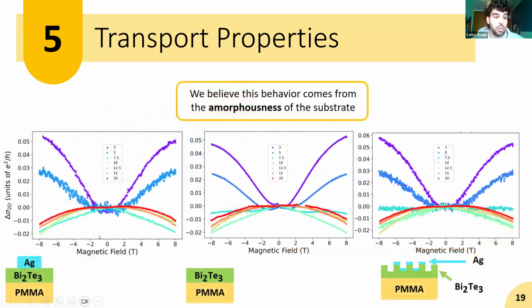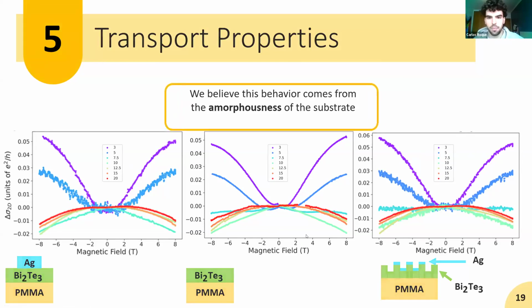We measured this sample again with the silver layer, then a sample with only bismuth tellurium, and then a sample with bismuth tellurium and silver but tailored with grating structures. And we verified that all data exhibit this competition between these two behaviors. So this competition does not come from the silver layer on top. We think that it comes from the amorphousness of the substrate, which is so amorphous that it localizes the electrons, and then the weak localization effect emerges because of that.